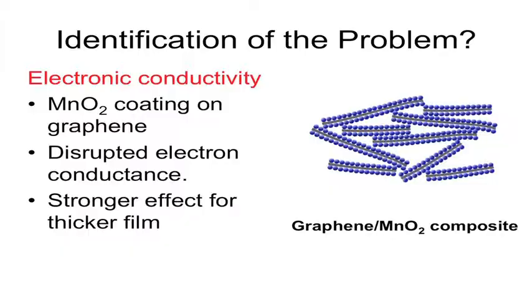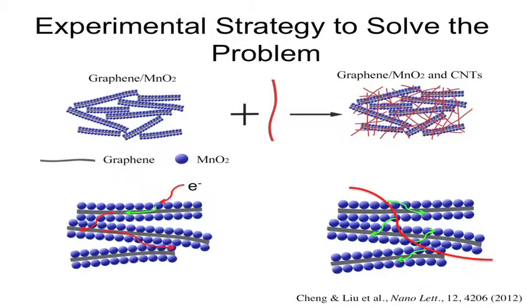People use carbon nanotube and graphene to improve conductivity of MnO2. Normally, they would have this carbon nanostructure, and they would glue MnO2 particles on it in order to have a very conductive material. But it turns out, once you glue materials on the carbon structures, you disrupt the connection path between the carbon structures, so you solve part of the problem, but not the whole problem. So what I found is that if I instead add an additional step by having MnO2 on graphene and then add a bare carbon nanotube, mix them together, I get a structure with a very good conductivity. And surprisingly, not only is the material very conductive, it's also very flexible and very, very strong.